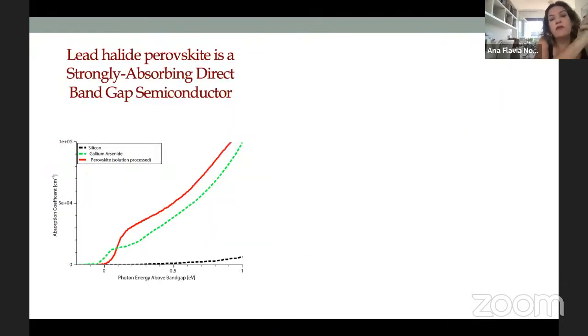In terms of absorption, these materials are really attractive for photovoltaics because the absorption coefficient of this material is very high. Here you can compare with silicon, which has an indirect band gap, and also with gallium arsenide, which has a direct band gap. You can see it's much higher even than gallium arsenide. So this is very nice because you can make very thin solar cells. For instance, in our lab, the thickness of our devices is just around 400 nanometers.